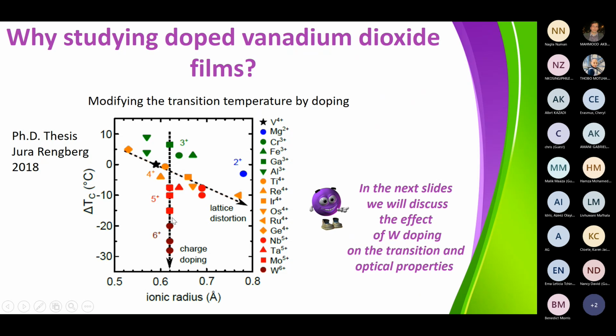And you can see that depending on the type of ions that you are going to use, you can either increase the transition temperature or decrease it. So typically, if you use chromium, you see chromium is typically here, or gallium here, you increase the transition temperature. But if you use an electron donor like tungsten 6+ or molybdenum 5+, then you will decrease the transition temperature.